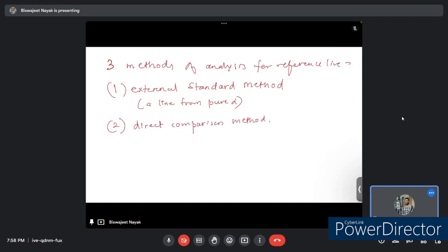So here K1 is basically unknown, and as it is related to I0 and I0 is unknown, K1 is unknown. But this I alpha becomes unimportant if the ratio of I alpha to the intensity of some standard reference line is formed, and then we can find the concentration of alpha from that.